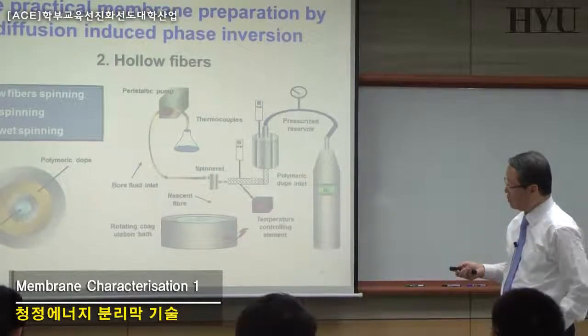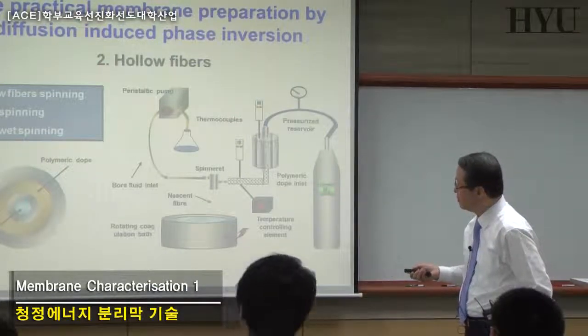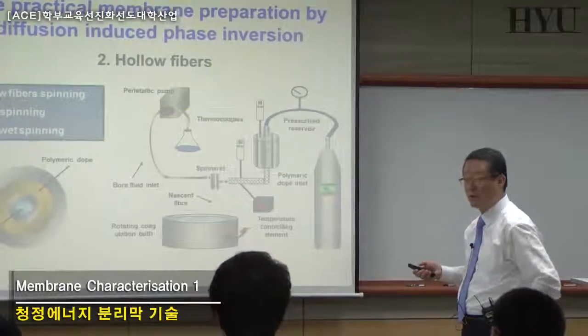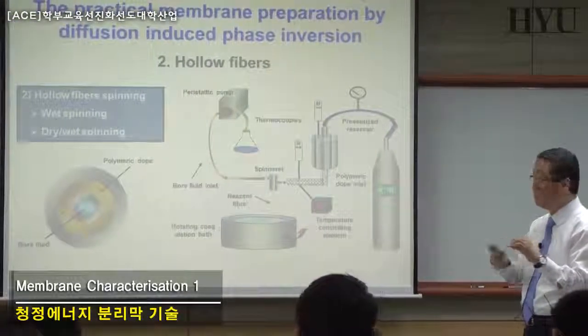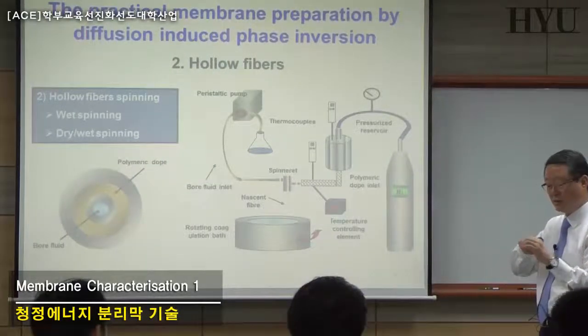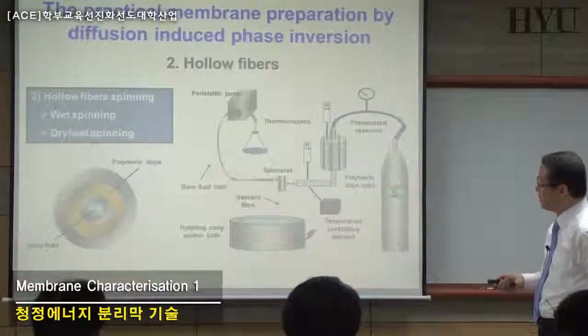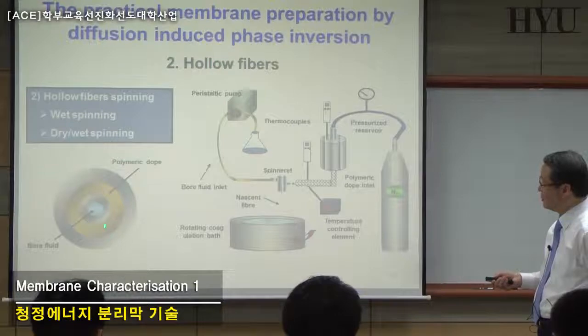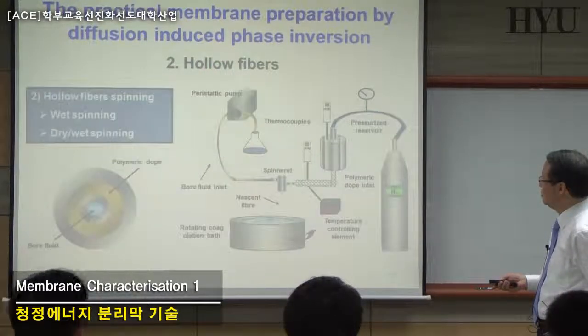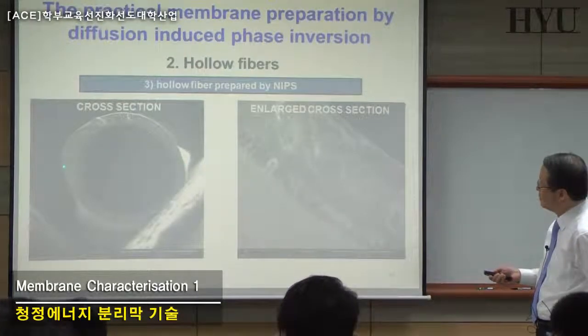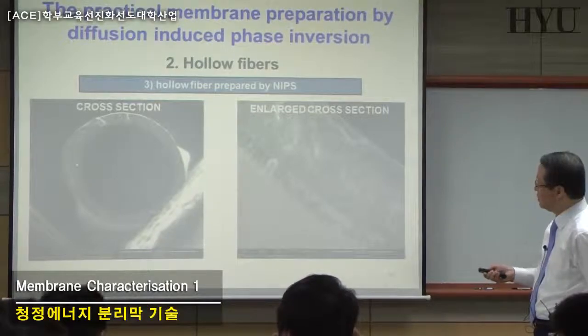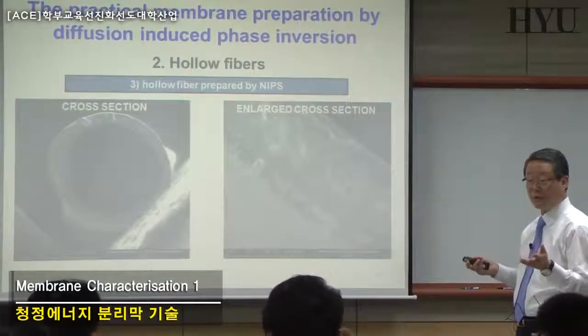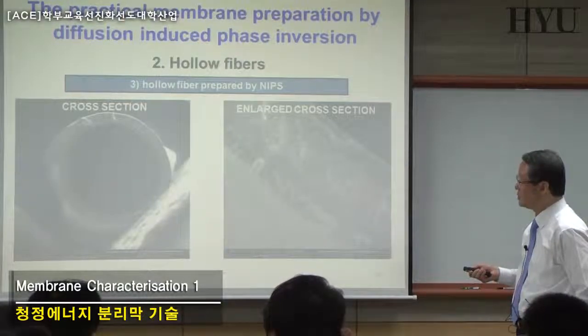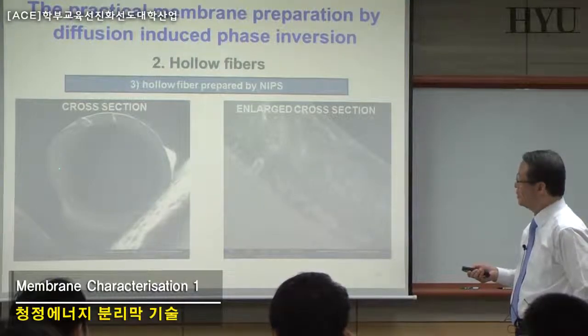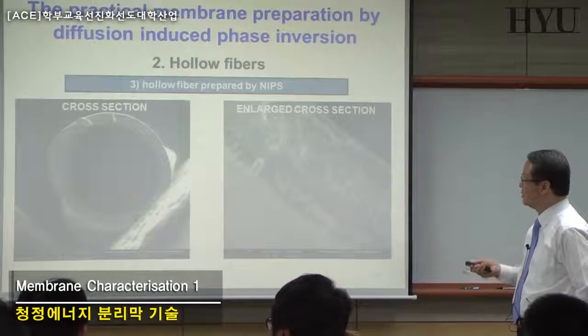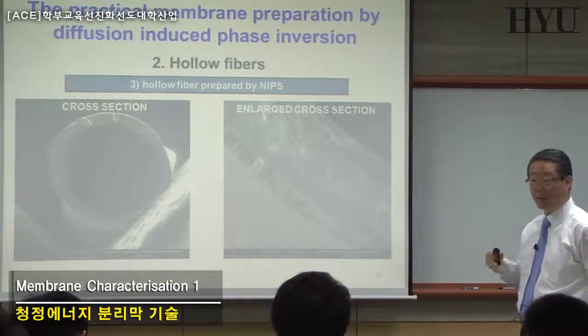Okay? For example, if you're having a fiber here, the yellow layer is actually the final hollow fiber layer, whereas this bore fluid is a hollow layer. So the total diameter, outer diameter, and inner diameter are very important. If you're thinking of the fiber, by knowing these two diameters, the outer diameter and inner diameter, you can calculate the wall layer thickness. The wall thickness ratio is defined as the outer diameter minus the inner diameter, divided by the outer diameter.